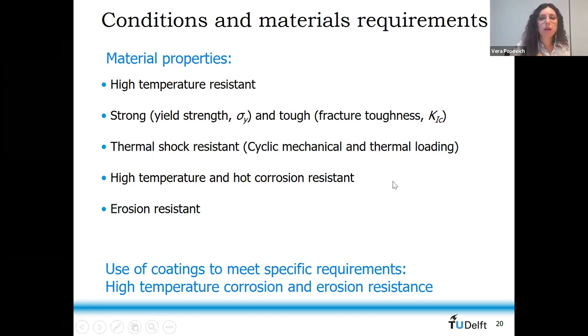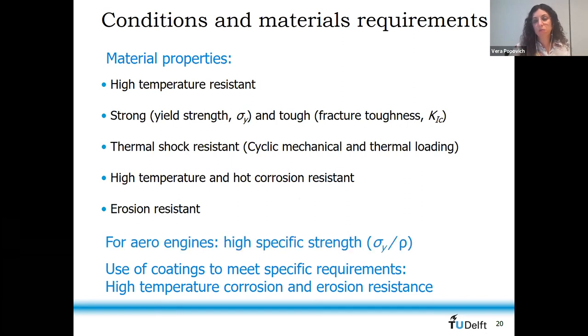Thermal shock resistance, so that's again, the material should be able to resist thermal shock. Quite often we see going from, let's say, anywhere between minus 50 to really extreme high temperatures. So this is a really high thermal loading, gradient and loading, high corrosion resistance and erosion. And in a lot of these applications, the use of coatings is required to meet these conditions, especially with respect to high temperature corrosion and erosion resistance. And that's where the thermal barrier coatings are used, which became very conventional.